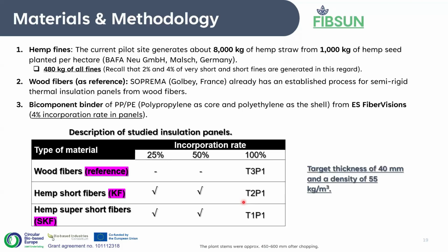And when we talk about the fines, as I defined before, they constitute 2 to 4% of the stock when it's processed. In this particular work, the batch of stock obtainable in a hectare of land is about 8,000 kilograms of hemp straw, and this is basically from 1,000 kilograms of hemp seed. What it implies is that 480 kilograms of fines are obtained as fractions from processing the stock. And this is where the goal of FIBSUN comes in again: how to use these fines. These fines need to find use, because otherwise we don't achieve the whole point of circularity and whatnot.